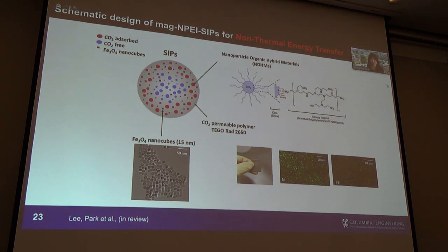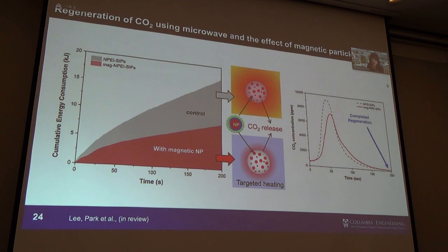I think it's a very interesting discussion we are having now, because by using non-thermal energy transfer, we can really achieve targeted heating. If we can imagine the CO2 capture reactor and the solvent regeneration reactor operating at exactly the same temperature, with only localized heating in the regeneration reactor, that will be the ultimate minimum energy input for carbon capture. So we developed this in SIPS material going back, but we incorporated magnetic nanoparticles, which are really good at absorbing microwave energy. And when we actually did the regeneration, as you can see on the right-hand side, instead of regenerating this material using steam for tens of minutes, half an hour or an hour, we were able to regenerate this material fully within a minute. And as you can see on the left-hand side, the amount of energy required to regenerate the same amount of CO2 was significantly reduced, which shows it could be a very effective design for CO2 capture.